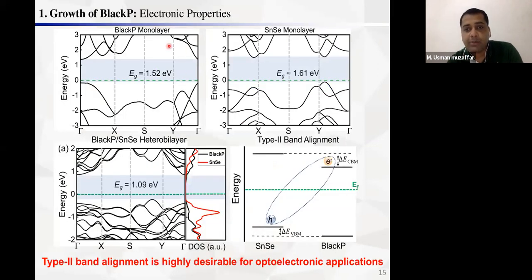So these are the electronic properties, the band structure of a black P monolayer, and you can see that there is a direct band gap at the gamma point, and in the SnSe it is an indirect band gap with a band gap of 1.6 eV. But after making the heterostructure of black P and SnSe, the band gap decreased to 1 eV. But the interesting thing about this heterostructure is that it forms a type 2 band alignment. As you can see, it can be characterized from this one.